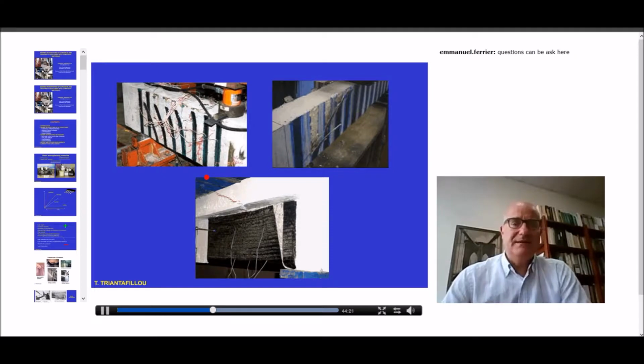I said before that this effective stress in the fibers used in shear strengthening depends very much on the failure mode. And you can see here what happens if those jackets are not closed, if those fibers do not follow the profile of the cross-section, do not go around the cross-section. When the shear crack forms, it's not very clear in this photo, I'm sorry. You can imagine that there is a diagonal crack here. When that crack forms, then those fibers, those strips debond. The same is the case with the fabric. If you have a diagonal crack here, the fabric will debond due to the fact that the fibers are subjected to tension and they are not anchored. That can be prevented if those fibers would be continuous all around the cross-section.